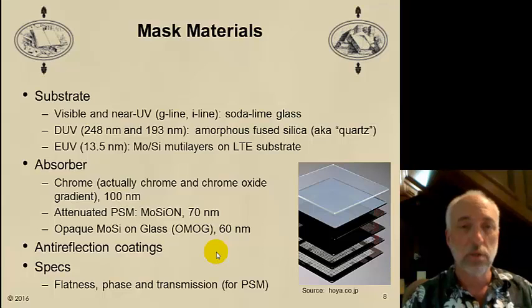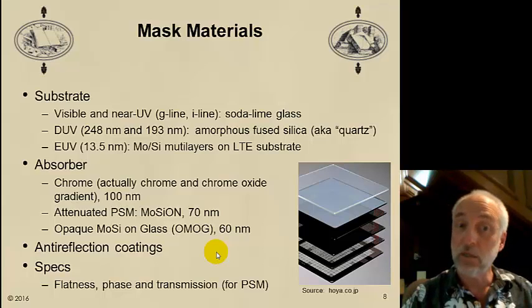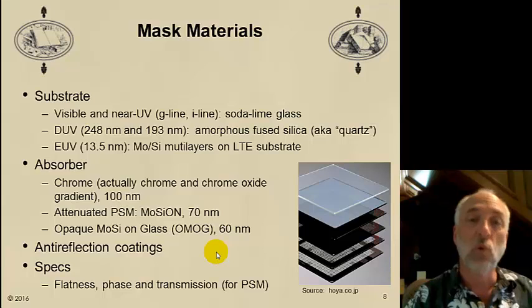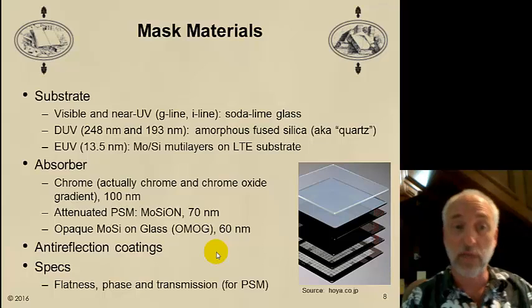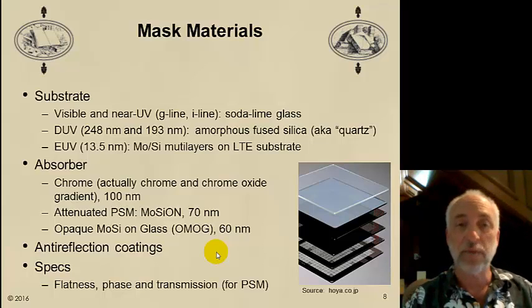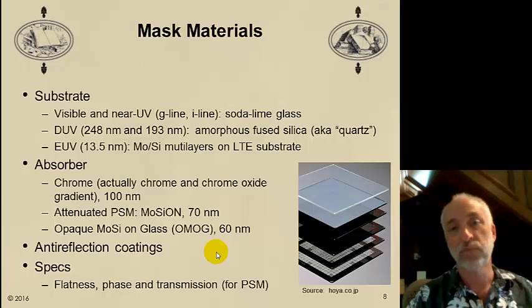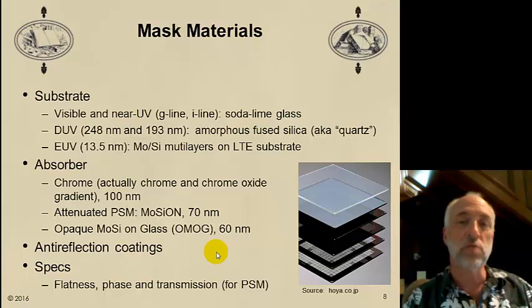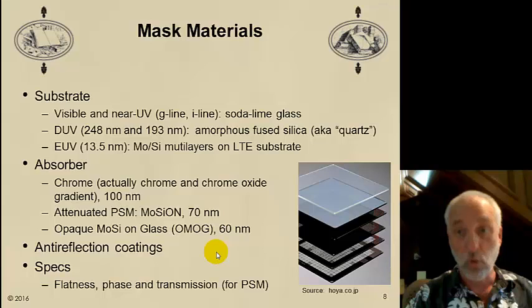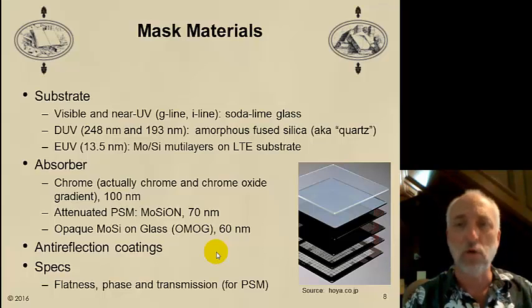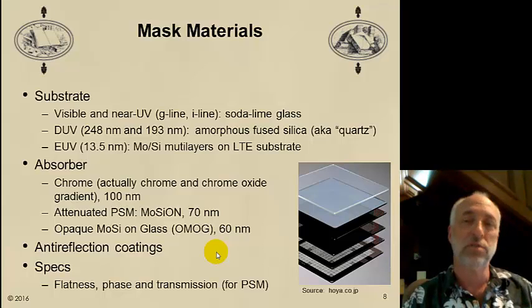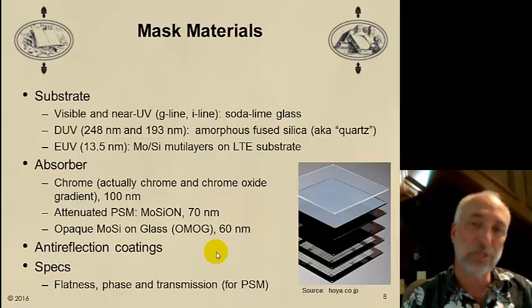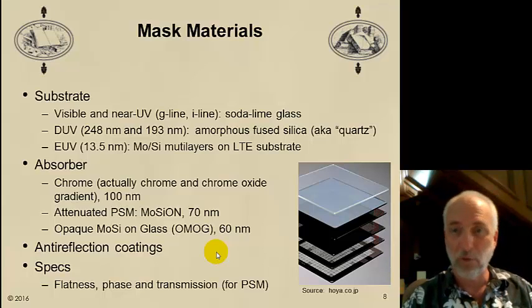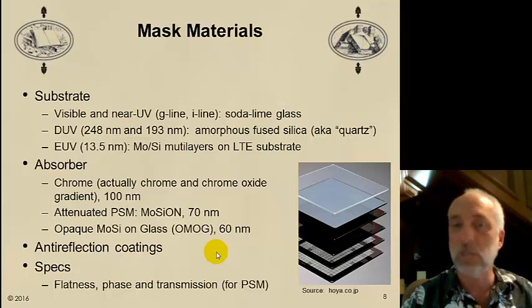It's very simple kind of glass, but as the wavelength shrank, we needed more sophisticated materials that transmitted light at these lower wavelengths. So at the deep UV, 248 nanometers or 193 nanometer wavelengths, we have switched to amorphous fused silica. It's a synthetic quartz. Now we call it quartz, but don't be fooled, this is not a crystalline material. Quartz is really a crystal. These aren't quartz. For some reason, we always call them quartz in our industry, but they're amorphous fused silica.